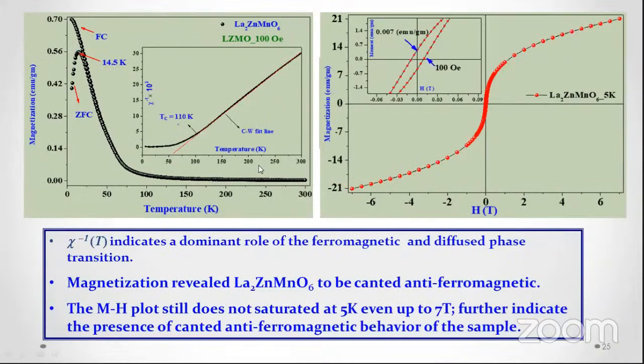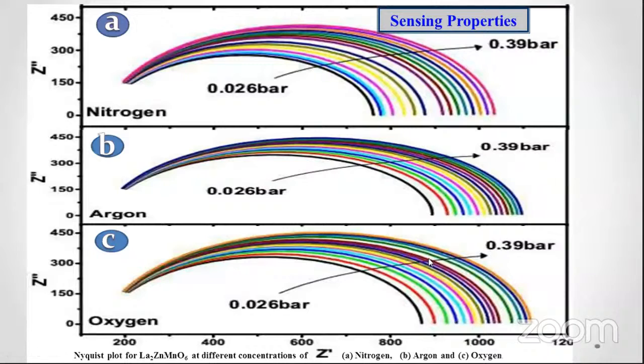And this is magnetic property. In magnetic property, we have fitted using Curie's law. And this is the magnetization versus magnetic field. So very low value of coercivity and low value of remanent magnetization is observed in this case. And this is the sensing property, how this is used as a sensor.